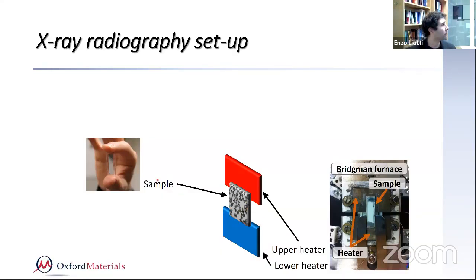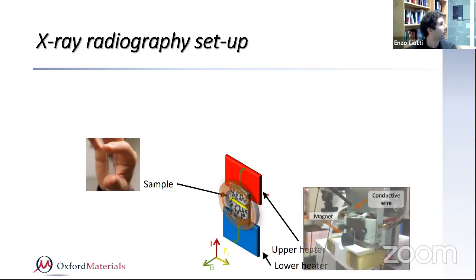By putting the sample in the middle, like you can see here, you can control the solidification. Furthermore, our rig allows us to put a little electromagnetic stirrer that moves the liquid in the sample while you are actually imaging the formation of the dendrites or the solid. That's done by putting a small ring magnet and connecting two wires to the sample from the bottom to the top. By passing a current into the sample in the presence of a magnetic field, you can apply a Lorentz force, which is controlled by the type of electrical pulse you put in.